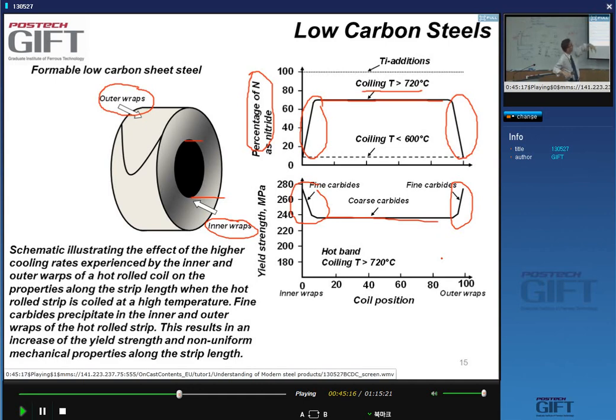And here, the nitrogen is basically not precipitated in the outer wraps. Yes? So the outer wraps age very quickly, and give you a lot of problems in critical parts where visual appearance and the absence of yield point elongation is essential. So what can we do? Well, obviously, one of the things to do is to just get rid of carbon and nitrogen, right? Because this problem is due to the carbon, and this problem is due to the nitrogen, right? So let's get rid of them. That's the solution. And that's indeed what happens.